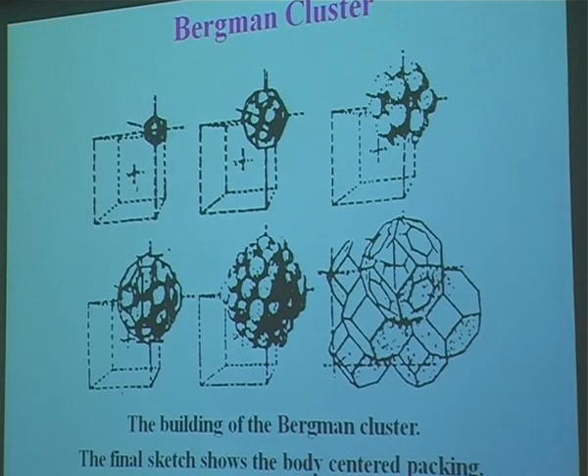And of course, what he took was the Pauling compound, the Bergman compound, the building of the Bergman cluster. He saw this picture in a Russian edition and saw that since it contains icosahedral clusters, if you cool such an alloy very rapidly, you should get quasicrystals. I think this is one of the best papers that has come out of India, to think completely differently. He was isolated in Benares. He was not reading all the papers that were appearing, but yet could sense immediately as he saw that. And this could form the basis for the synthesis of quasicrystals.